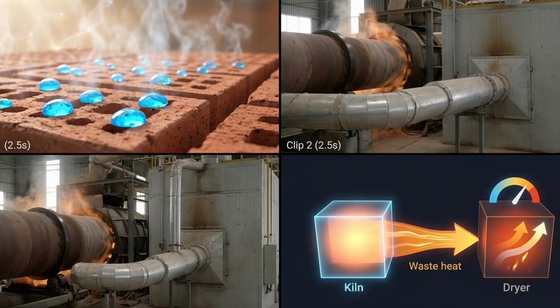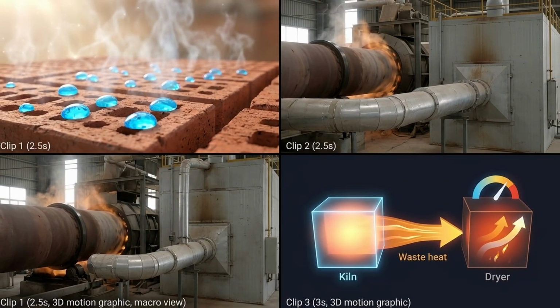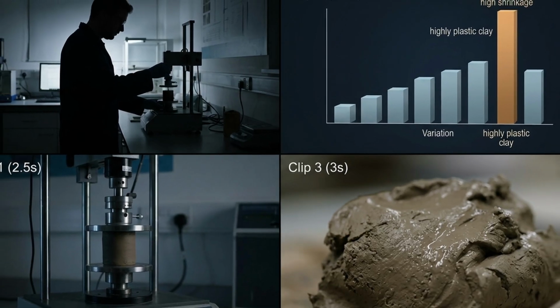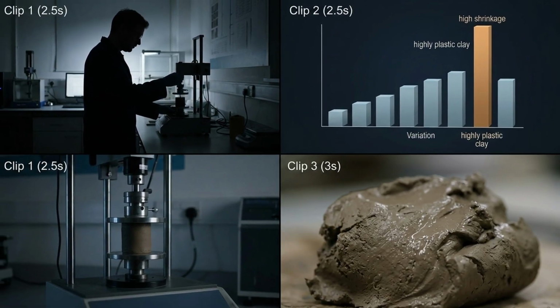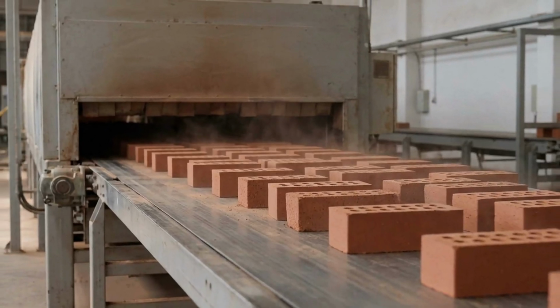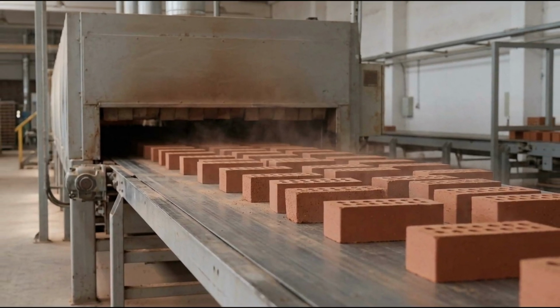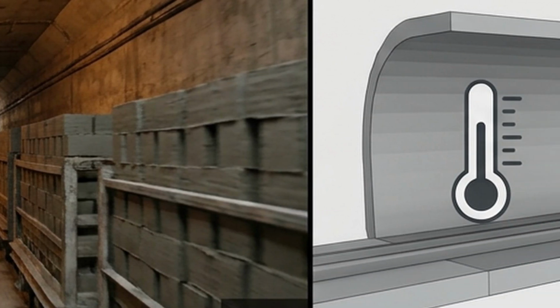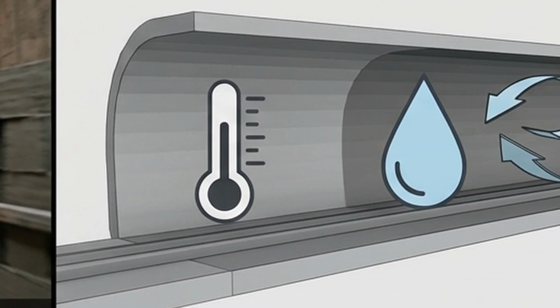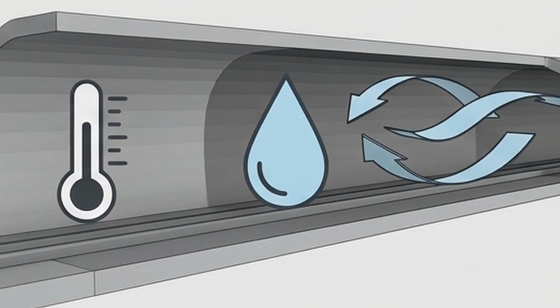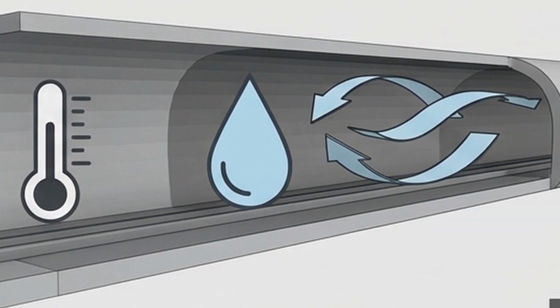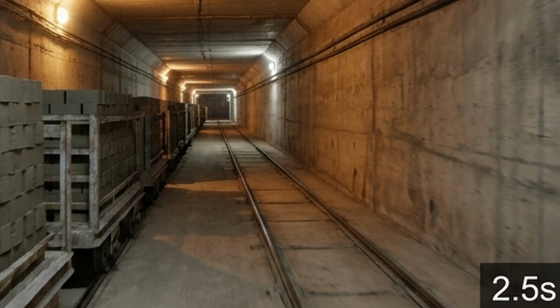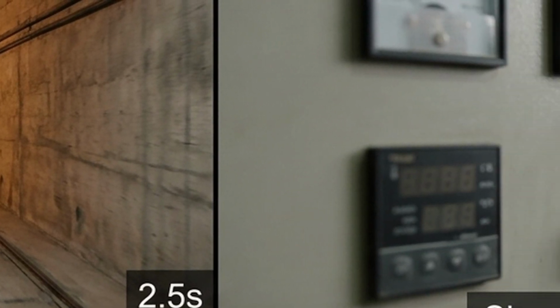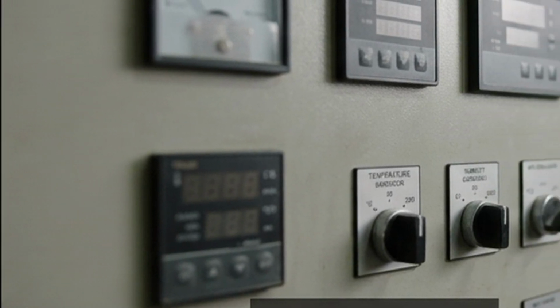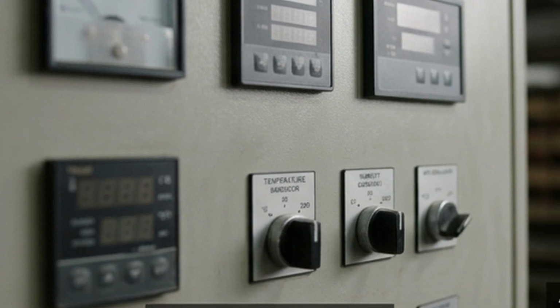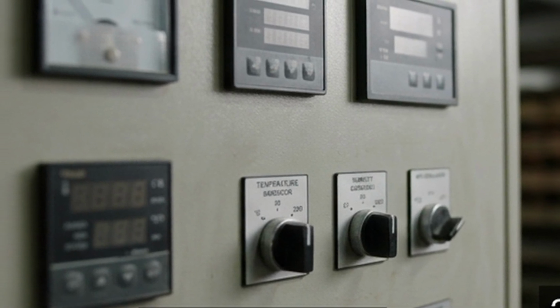Humidity control is constant. Some plants use sensors to measure water content, thermal cameras to detect cold spots, and automated systems that adjust fans and burners. Air circulation must reach all sides of the brick. If one area receives less airflow, it remains damper. If another receives too much heat, it dries prematurely. The uniformity of drying defines the quality of the kiln, because a brick with excessive internal moisture can burst during firing when the trapped water turns to steam.